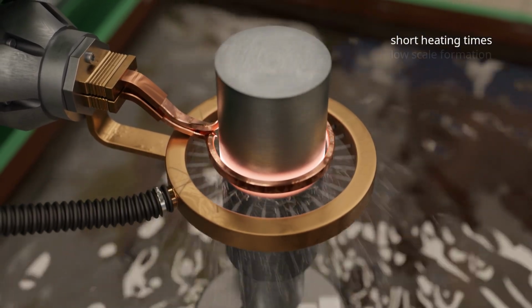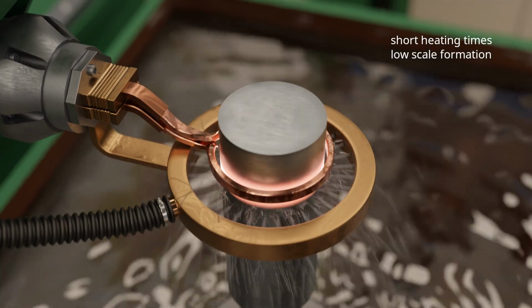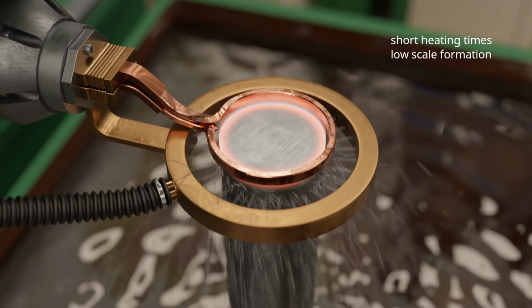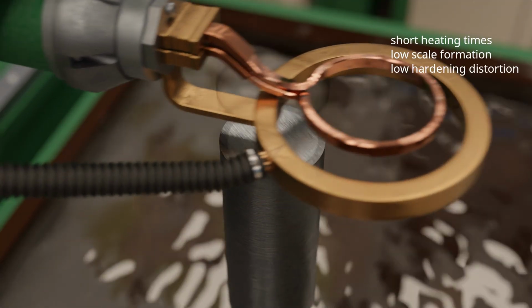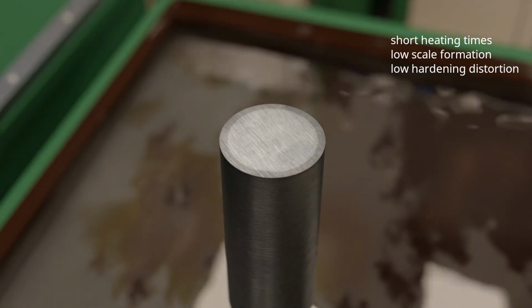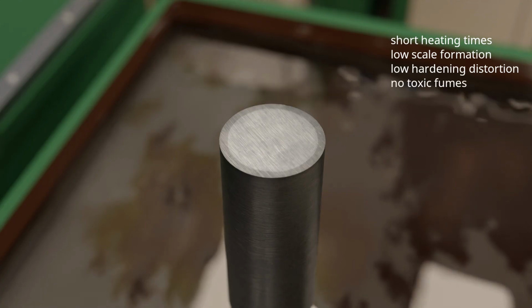This has the advantage that scale formation is relatively low and the amount of post-processing required is reduced. The risk of hardening distortion is also greatly minimized. In addition, induction hardening does not produce any toxic fumes, as is the case with flame hardening. Another advantage of induction hardening is the more even heating of the surface, provided the inductor is optimally adapted to the workpiece. However, this requires a high level of tool design in advance, meaning that induction hardening is particularly economical in automated production lines with large batch sizes. Due to the high electricity costs, cost-effectiveness increases if only small areas of a workpiece need to be hardened.